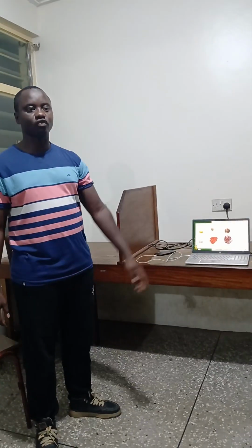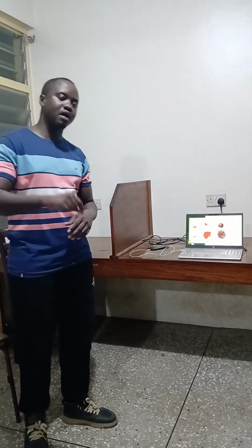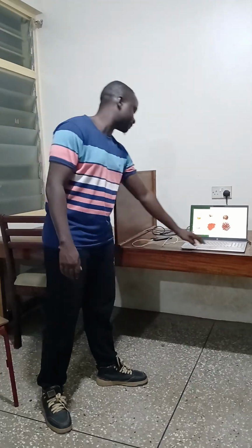And then we introduced the carbon quantum dots. Of course, the carbon quantum dots had been enhanced before its introduction. So we added 10 ml of the carbon quantum dots to it. As you can see, the color changed from the yellow color of the seaweed extract to the dark brown color for the one with carbon quantum dots, and to the light brown color for the one without carbon quantum dots. These were the machines and instruments that we used. We used XRD, an electrochemical workstation, and we also used a particular design as our electrochemical cell there.